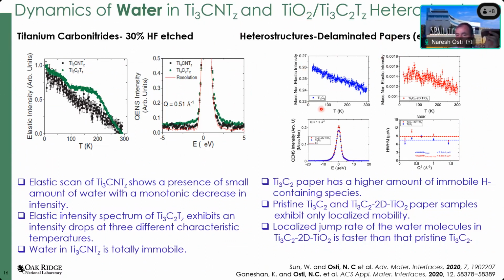What we found is that in the case of the pristine paper, the intensity is significantly higher compared to the MXene heterostructure, indicating that there is a lot of hydrogen-containing material. And then we also collected the QENS signal. We analyzed the QENS signal and plotted it as a function of the square of the momentum transfer. What you see here is that, compared to the previous cases where you could see strong Q dependence, here the half width at half maximum is not showing Q dependence. It is kind of flat. It means that the water molecules in this sample are totally confined. They are not moving over a long distance within this sample on the time scale. That's what we figured out in terms of the MXene papers.